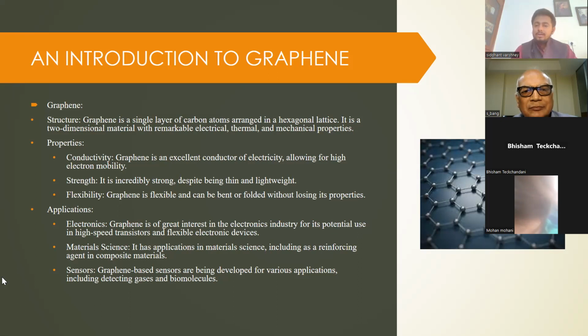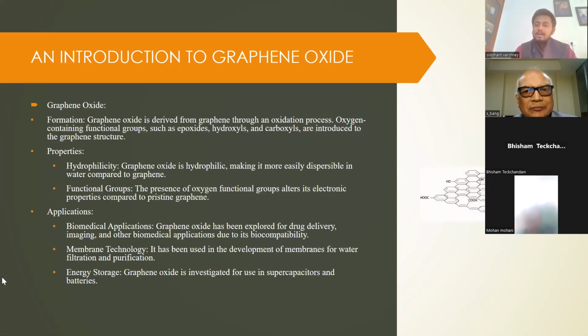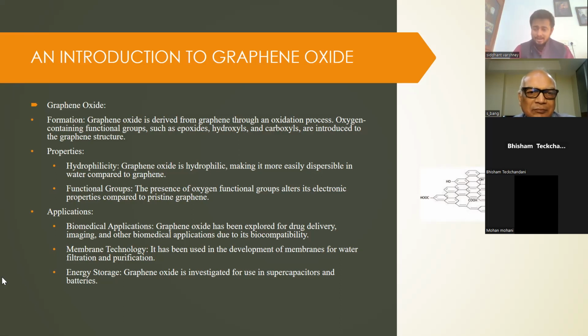Now the brother of graphene is graphene oxide. Graphene oxide, as you can see, the structure is nothing but graphene, but having oxygen functionalities: hydroxyl, carboxyl, and epoxy functionalities. So these are the only 3 functionalities that are there in addition to graphene. Its application, so it is basically a hydrophile, that means water loving. So it disperses very well in aqueous mediums, in comparison with graphene. For graphene, there are solvents like NMP, N-methyl pyrrolidone. But graphene oxide can be dispersed even in water. Normal tap water also it can be dispersed.